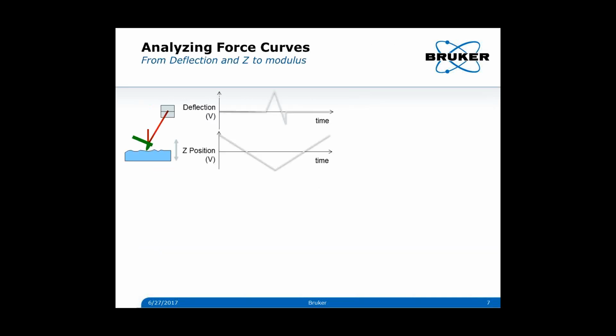Okay, so in terms of the calculation of the modulus in particular, let's look at how we do that, and then we'll do an analysis of the error that can accumulate during this calculation. So the first thing we do is we collect deflection of the cantilever and Z position as a function of time. And in force volume, where you're doing linear ramping, it'll be a straight line going down. You'll have a deflection versus time plot that looks like this, where it's not touching initially, and then it comes into contact, and then eventually it breaks free, and then it's off the surface again.